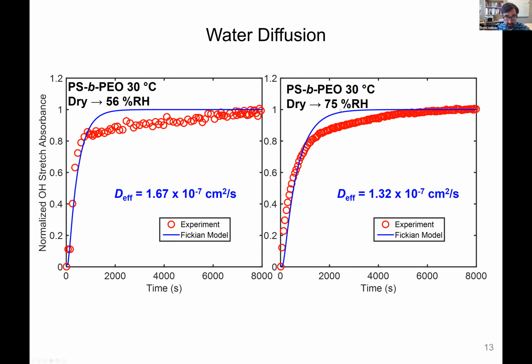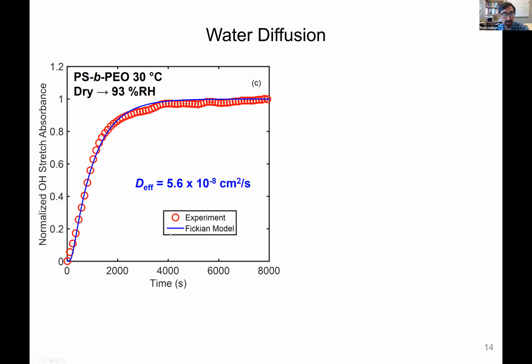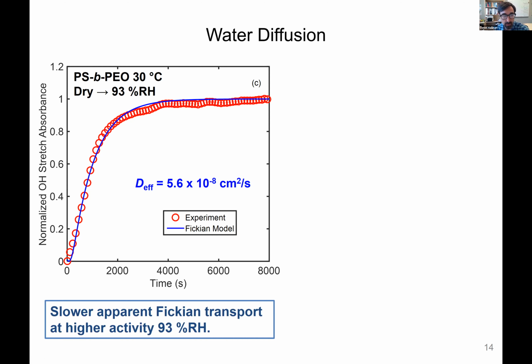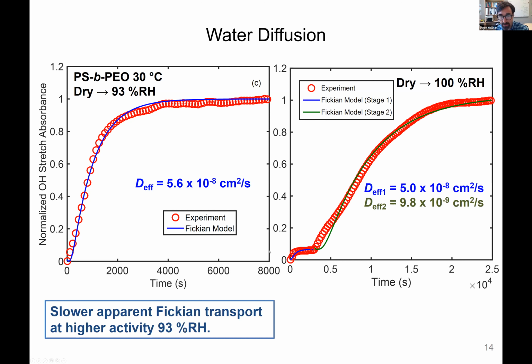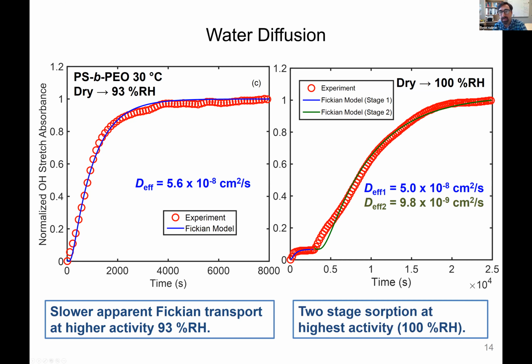At medium to moderate humidities, interestingly, when we go to higher humidity, the apparent transport, the apparent diffusion looks to be Fickian according to the agreement between the model and the data. And if we go to 100% RH, what we see is actually two-stage sorption: a Fickian sorption and then a much larger sorption at higher humidity. We think that the second stage, which is much slower but takes up a much larger amount of water, is due to actual swelling, macroscopic swelling of the polymer that doesn't happen at lower humidity.